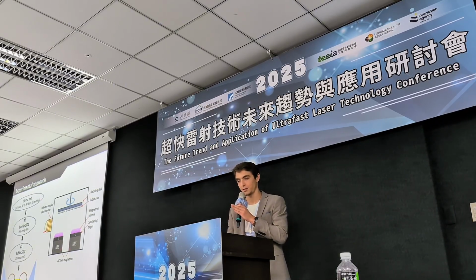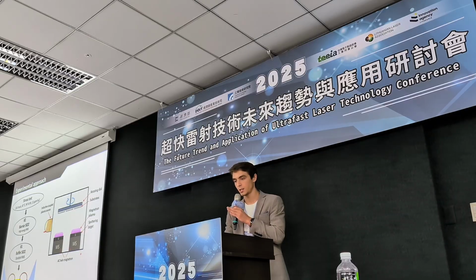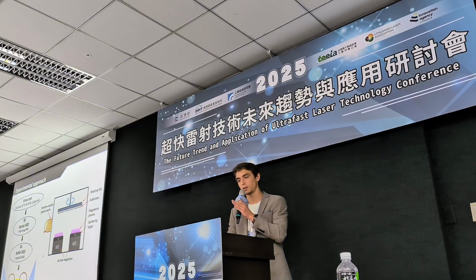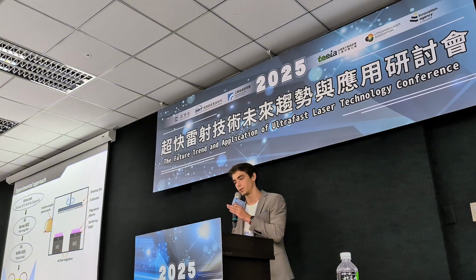Talking simply, in this concept the buffer silicon dioxide protects the LED from the deposition of barrier silicon dioxide, and the barrier silicon dioxide protects the LED from the environmental stress test. Both times silicon dioxide was sputtered using an AC twin magnetron in a reactive magnetron sputtering process, but the second step was additionally assisted by inductively coupled plasma, which increased the plasma density and the mobility of sputtered atoms to densify the film. So, the first step is standard reactive magnetron sputtering, and the second step is high-density plasma reactive magnetron sputtering. That is the topic of today's presentation.